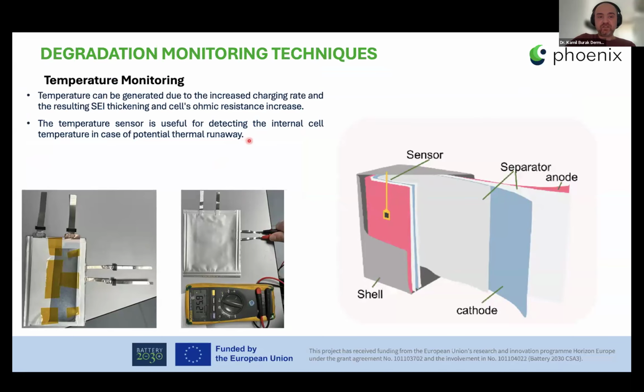Degradation monitoring techniques that we use in the PHOENIX project include temperature monitoring. Temperature can be generated during the operation of the cell, and it is even worse at an increased charging rate, which results in SEI thickening, and the cell's ohmic resistance will also increase. So the temperature sensor is useful to detect the internal cell temperature, especially local changes in the cell temperature, to prevent thermal runaway of the cell. These are some of the images showing how we use the temperature sensors in our project.